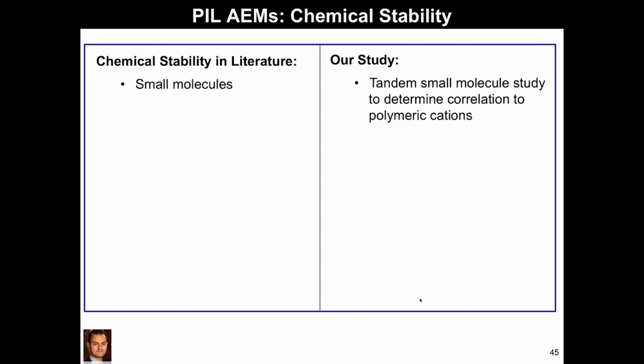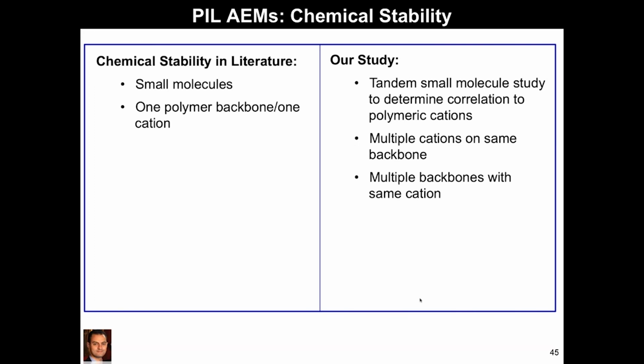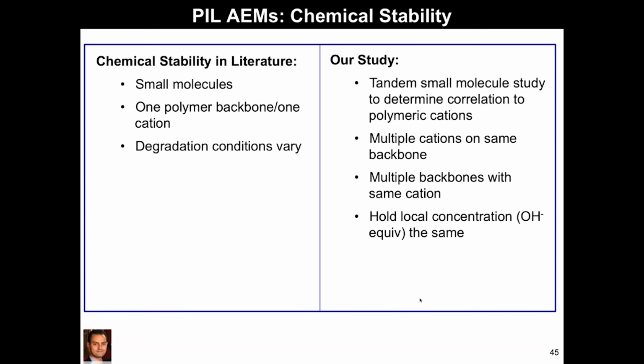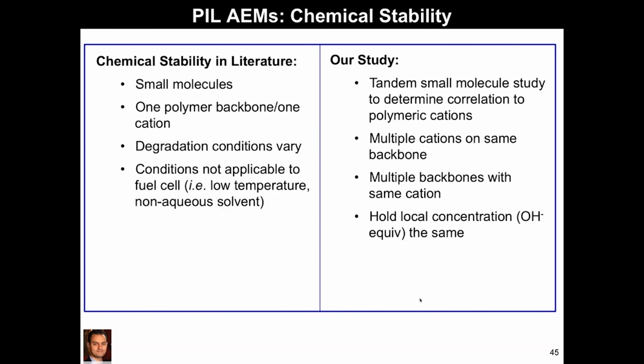So we want to do a study where we look at small molecules and polymers in tandem. And many studies that we saw only would look at one polymer backbone and one cation. So what we wanted to do is look at many cations on the same backbone and many backbones with the same cation. We also noticed in the field that their degradation conditions vary. So what we wanted to do was have something very constant. So we held the local concentration or the equivalence of hydroxide the same. And then also some of the conditions we saw were not very applicable to fuel cells. So some people would use non-aqueous solvents. So we wanted to mimic fuel cell conditions a little bit better.